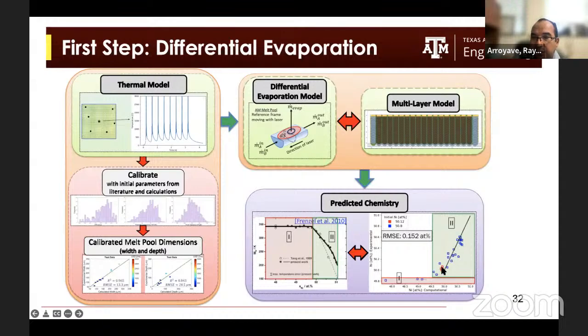So here is a comparison of the experimental nickel loss, measured by measuring the transformation temperature of these shape memory alloys, with the computational predictions. The agreement of 0.15 atomic percent in error is actually smaller than the resolution of chemical analytical techniques such as EDS or WDS, right? So we're able to build predictive models that are more precise than some analytical techniques to measure the local composition of materials as they are printed, okay?